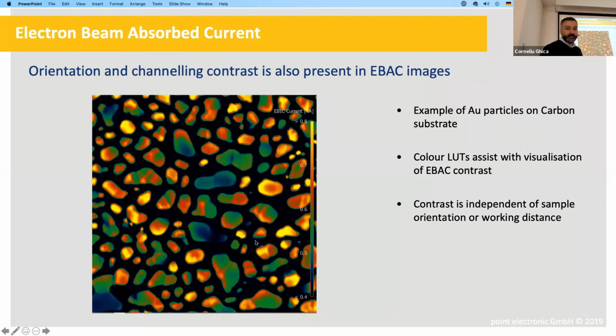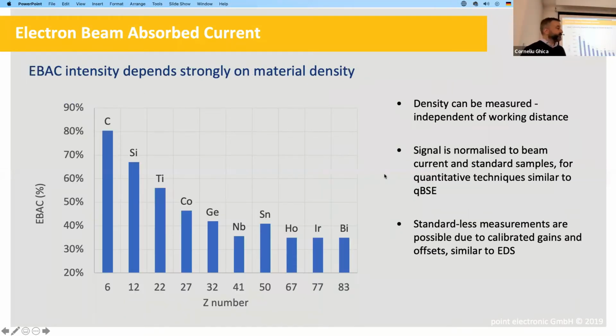Another important point when we do these techniques based on electron beam currents is that they depend on density. Here I'm measuring the percentage of the current absorbed into the sample as a function of material Z number. Of course, the lighter the material, the more current we absorb. The denser the material, the more electrons we backscatter and the less is absorbed. So the intensity of the signal depends on the material density.